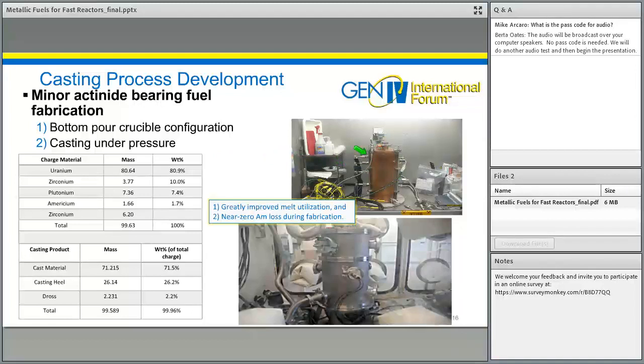We started actually with the drawing of the furnace I showed in the previous slide. We fabricated one of these units and used it for a number of years just in a hood to make testing go that much more efficiently. We did cast with uranium in the hood, but we used various surrogate materials to simulate other constituents. We used manganese as a surrogate material for americium, having a very similar issue with volatility.